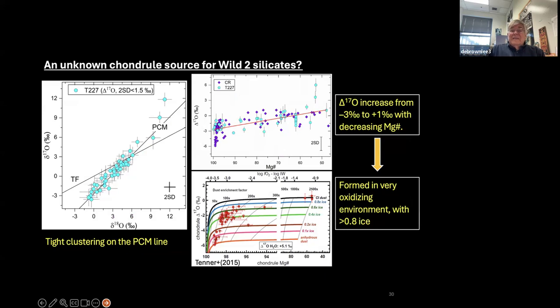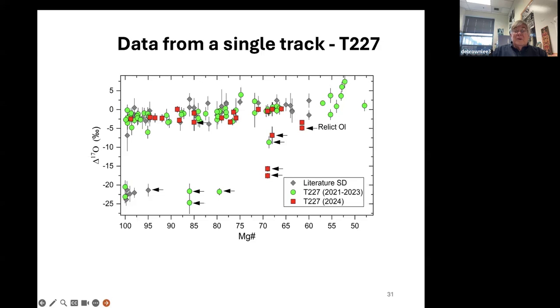The upper right again shows this cap delta O17 increase with increasing iron in the olivine, or decreasing magnesium number, and it goes from about -3 per mil to about +1 per mil. This implies that some of the materials formed in very oxidizing conditions, presumably with a fair amount of vaporized ice or vaporized silicates in order to produce the oxidizing conditions.